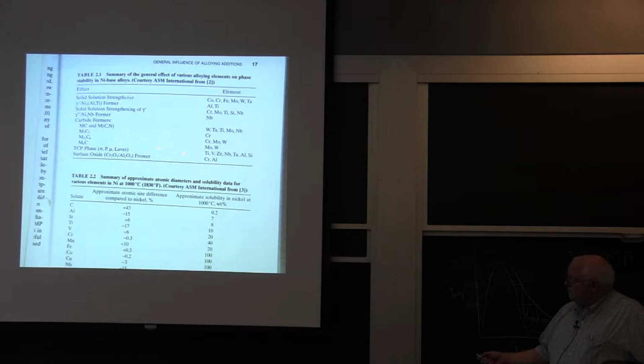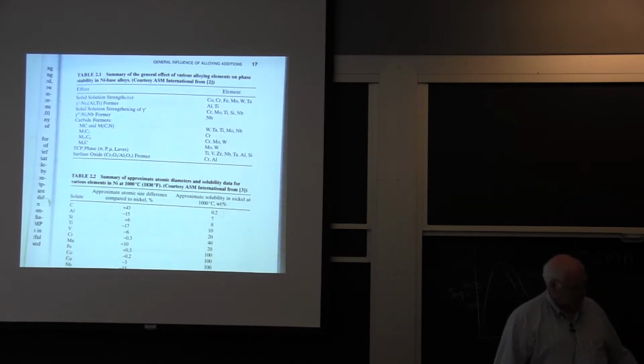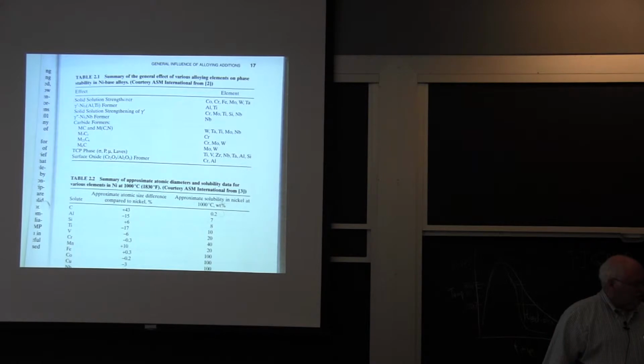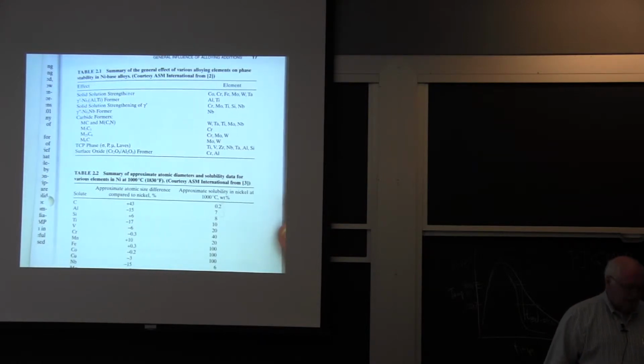So far as surface oxidation, when these things are used at high temperature, it's chromium and aluminum that are the primary things which form chromium oxide and aluminum oxide scales. If you analyze the surface oxide on these high temperature nickel-based superalloys in jet engines, they will be chromium oxide or aluminum oxide, depending on the ratio of the two, nearly pure. Just like stainless steel, it's nearly pure chrome oxide. On these nickel-based alloys, it's either chrome oxide or aluminum oxide, depending on the composition. Okay, so that's sort of an overview of the metallurgy of these things.